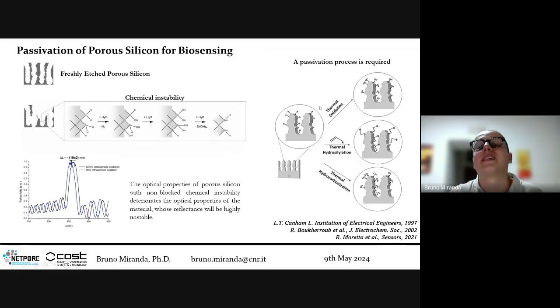The first one is thermal oxidation. Here, instead of avoiding oxidation, you totally oxidize the surface of the pores. In this way, you have silicon dioxide on the top layer of the pores, and there is no chance anymore to degrade this material because silicon dioxide is very stable, and you do this with a thermal treatment.